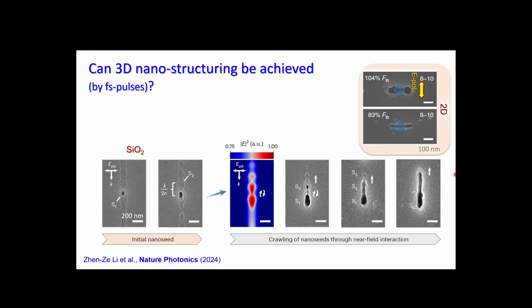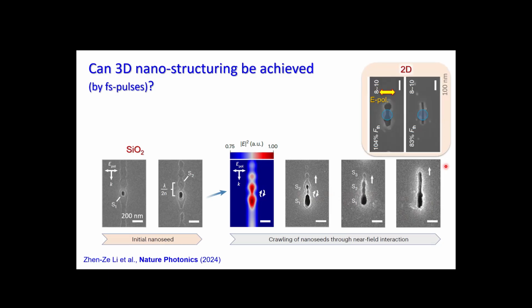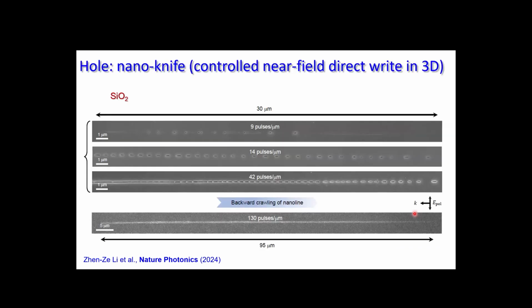Let's remember this from the writing on the surface. This was a lithography task, but now let's turn it in this orientation to have the same orientation of polarization. So this type of patterning is really happening here, only this is inside the bulk. Here is an example of how, by rotating many pulses, we can make them all into kind of interconnected volumes, which are nanoscale volumes. They are not expanding, and they are just taking place along the propagation of the Bessel beam.